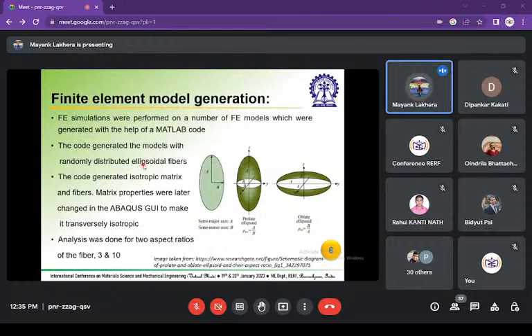Now to test the validity of this method when it is applied to a transversely isotropic matrix, we have developed a finite element model, which was generated with the help of a MATLAB code. We have tested this method on a prolate ellipsoid. A prolate ellipsoid is basically when an ellipse is rotated about its major axis. So this is a prolate ellipsoid, and this is an oblate ellipsoid. We have done our finite element modeling for the prolate ellipsoid only.